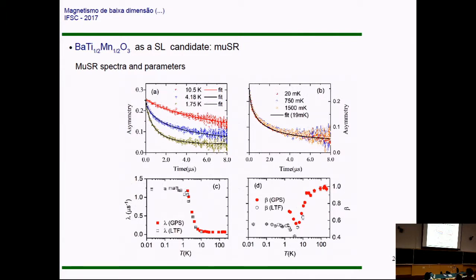So if you have some sort of ordered state, you would expect oscillations here in the muon decay. But here we don't see oscillations. You see something which simply decreases monotonically, and therefore there is no ordered state in this temperature range, and no indication of an ordered state or some sort of quasi-static magnetism in this temperature range.